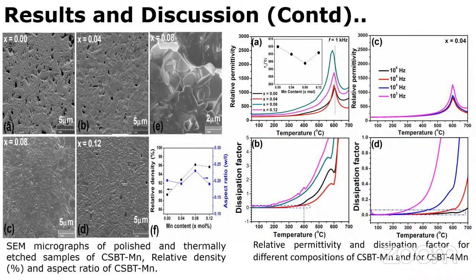Now moving towards the relative permittivity and dissipation factor. Here we have plotted different graphs of relative permittivity versus temperature for different compositions. TC came near 600 degrees Celsius for all the compositions. The dissipation factor was also low, up to 400 degrees Celsius, which means these materials are good for piezoelectric properties, and the properties can be improved further.